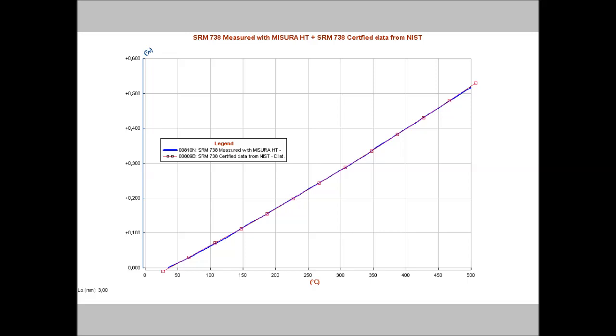This graph is showing the result of the measurement of the standard reference material 738, the blue line, supplied by the National Institute for Standards and Technology, NIST, in comparison with the data certified by the NIST, the red dotted line. Since it is not necessary to correct the curve with the correction curve, it becomes possible to use complex heating and cooling rates during the test. This makes it possible to reproduce industrial firing cycles.